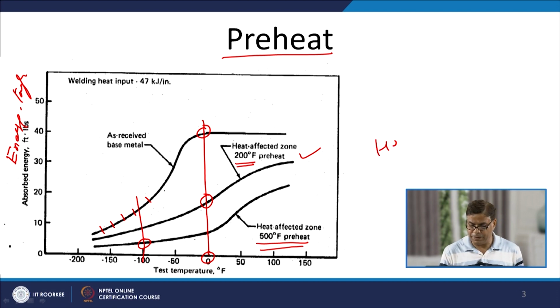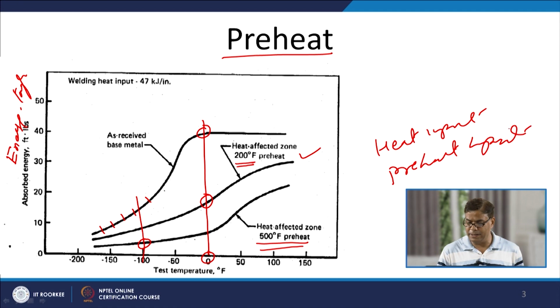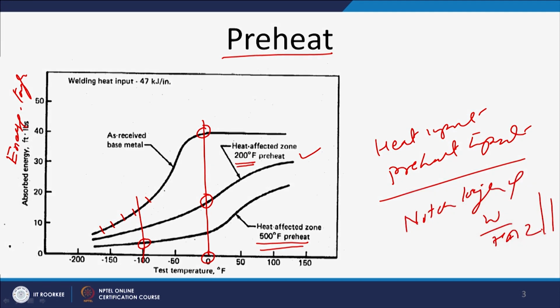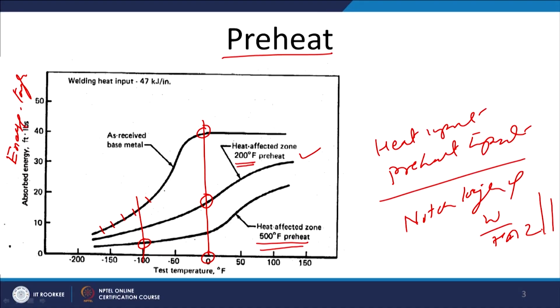So, many times the heat input during the welding and the preheat temperatures are identified considering the notch toughness of the weld as well as heat affected zone. So, the preheat temperature and the heat input are established during the welding procedure specification, that means the heat input and the preheat temperatures are established in such a way that the weld joint in the heat affected zone and in the weld metal has the minimum required toughness for a given